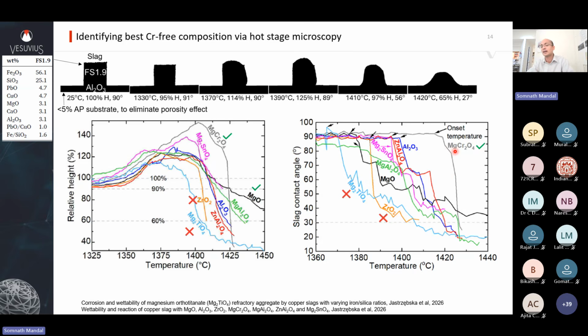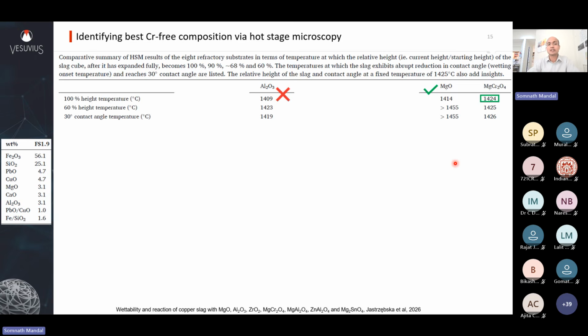The onset temperature is a lot higher, which means that magnesia-chrome is very good, and we also know that from practice. So if I try to summarize this in terms of tables, these 100% height temperatures are like the onset of the shortening of the slag pellet. You see that the temperature is very low, only 1409 for alumina versus magnesia-chrome is 1424 and magnesia is 1414. So clearly for magnesia, the refractory should be a basic brick, not an alumina based brick. That is the takeaway from this.